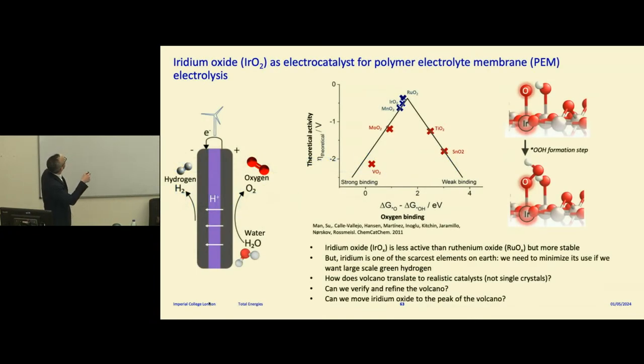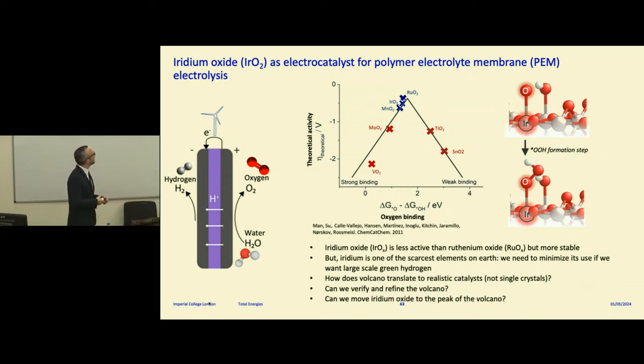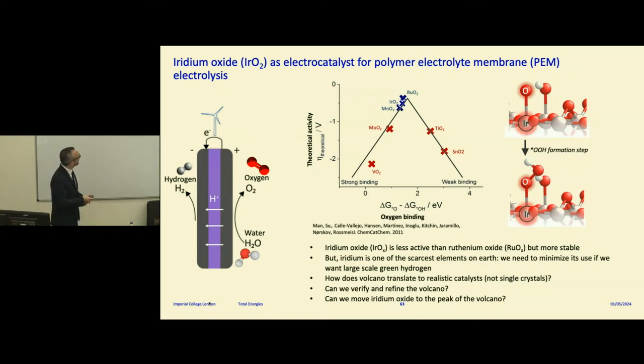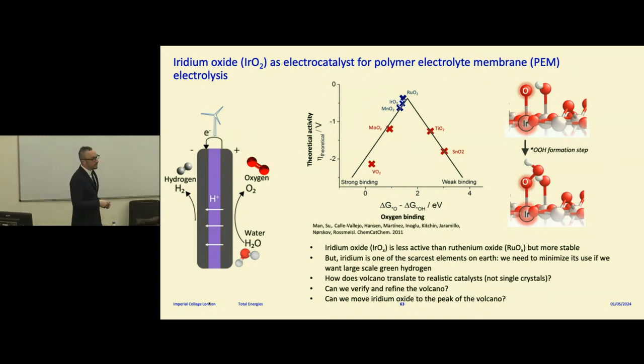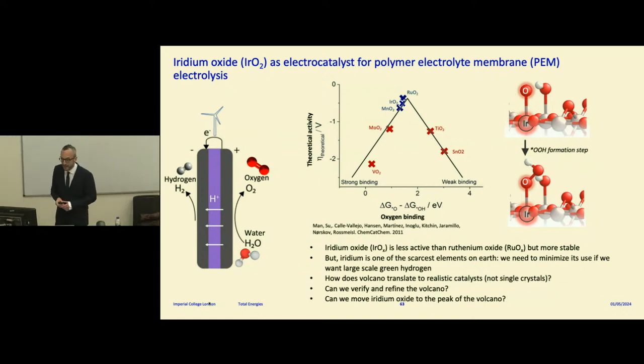One thing we started being interested in: I already mentioned ruthenium oxide is the best catalyst for oxygen evolution. We studied that and did some really nice research with Reshma, MIT, and the Technical University of Denmark. But the problem is, it tends to corrode away. As I mentioned earlier in my talk, iridium oxide is not quite the tip of the volcano, but works pretty well. The problem is iridium is one of the scarcest elements on Earth. So we need to minimize its use if we really want to make hydrogen at a large scale.